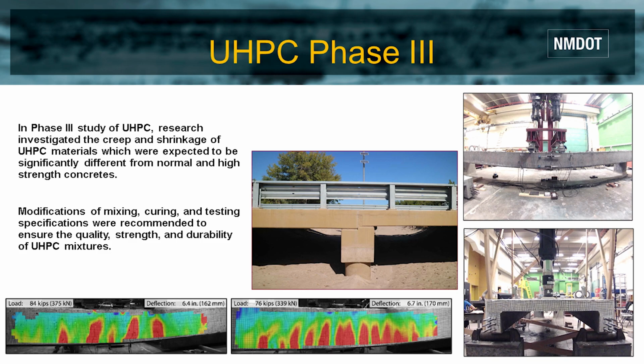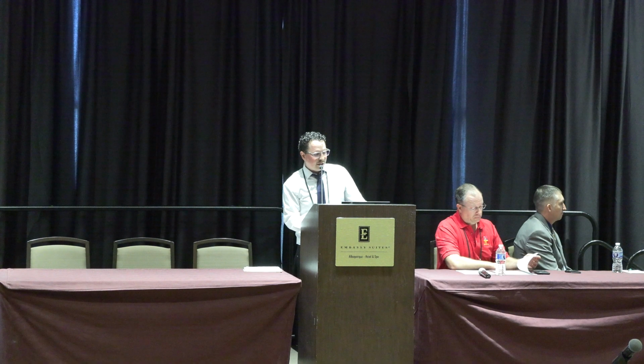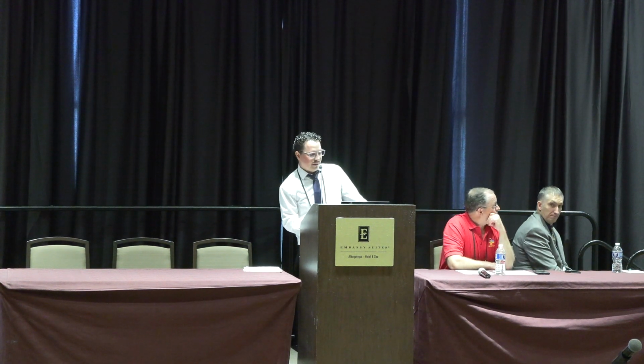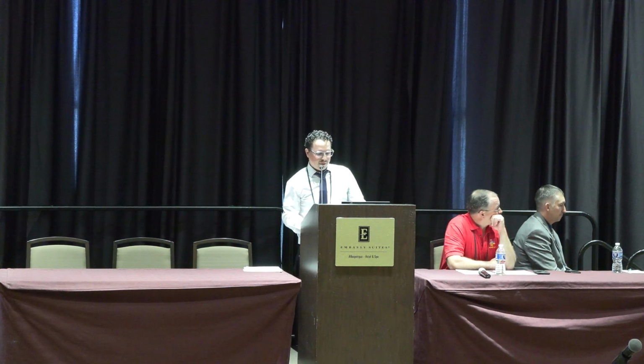So this bottom left image is a digital image correlation test that was conducted in the lab on a UHPC girder. And the one to its right is HPC. The red area depicts high tensile strain, with the blue indicating compressive strain. So we can see here that the ultra-high performance concrete is a little better.